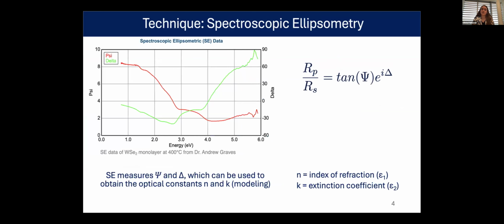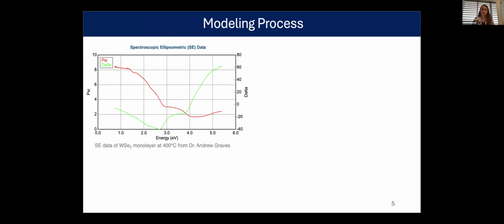The SE itself is a measure of the change in polarization of light that strikes the sample. The light strikes the sample and is reflected back into a detector, and it outputs this psi and delta spectrum. So these spectra can be modeled to obtain the optical constants N and K, being the index of refraction and the extinction coefficient. I use epsilon1 and epsilon2, which are not exactly equivalent one-to-one to N and K, but they do represent similar quantities. So to break it down further, we have this spectra of psi and delta.